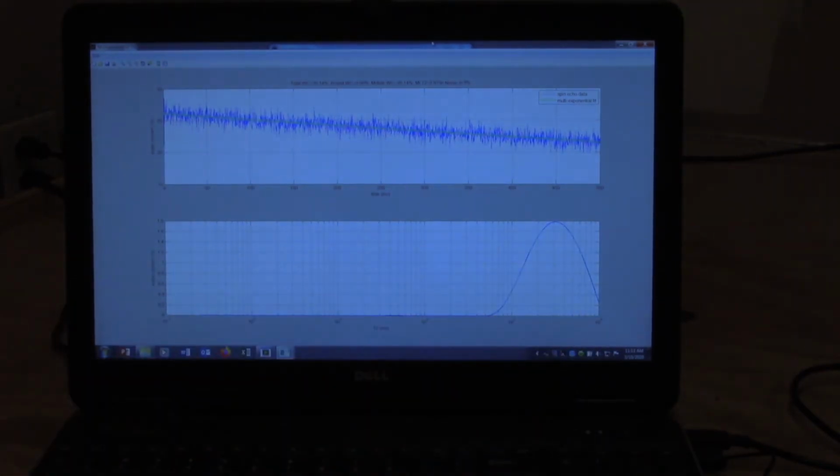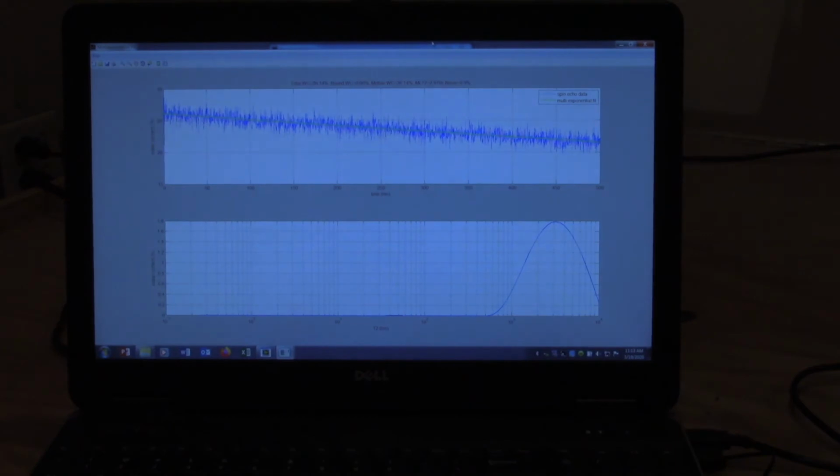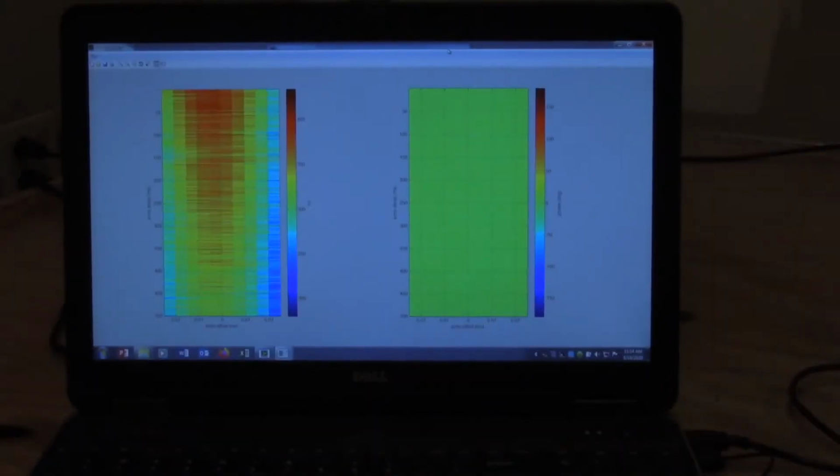And the bottom is the results of the inversion, where we have this distribution of relaxation times. This is associated with the exponential relaxation. In this case, we can see the peak of that distribution is really long, which is associated with that bulk water relaxation. At the top, it's reported total water content of 26%. So that's our calibration factor.